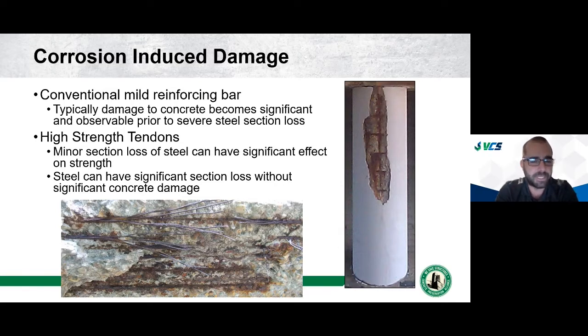Now, with pre-stress elements or post-tension elements, they're much smaller diameter. They have a lot more stress on them. So a little bit of corrosion has a much more significant effect on their structural capacity. So here's a pre-stressed beam. And you can see a spall has formed, and already we see completely broken strands in that spall. So for enough iron oxide to build up to create that spall, you have to have much more percentage section loss of those strands than you would in a conventional rebar situation.